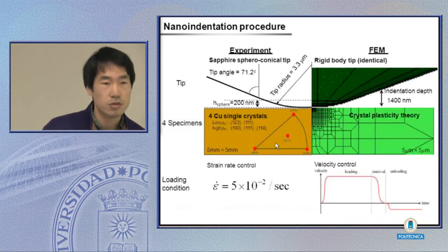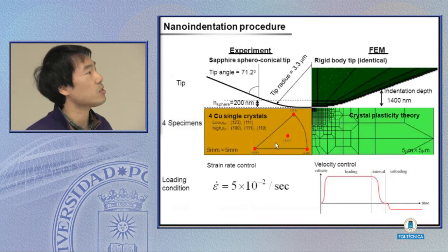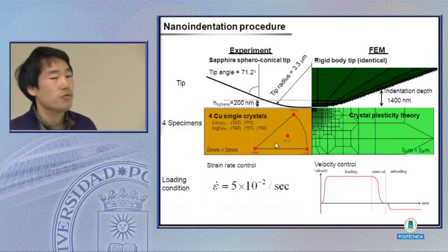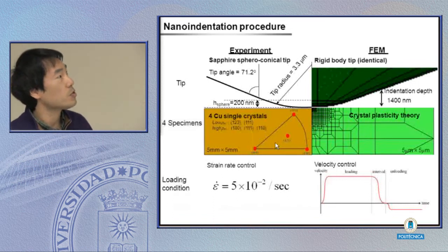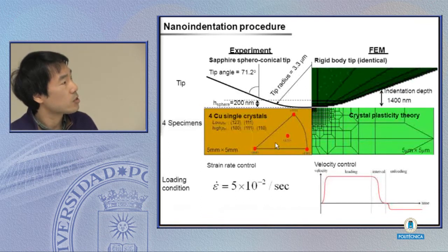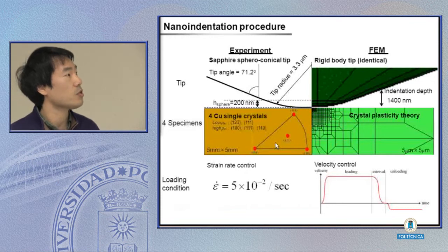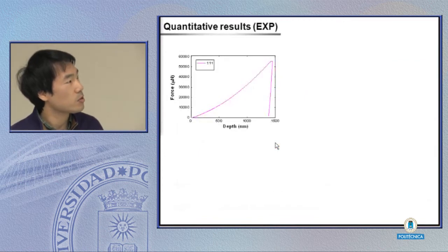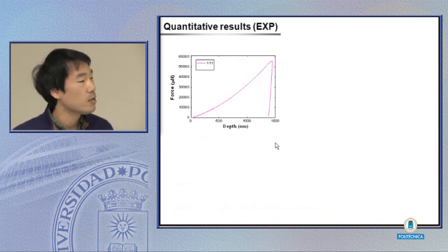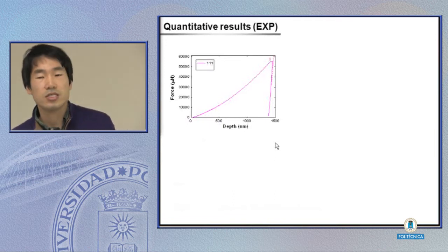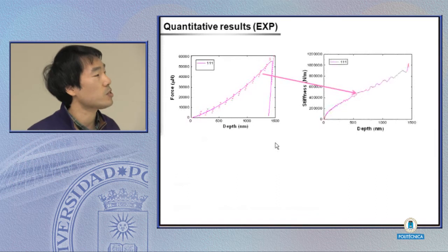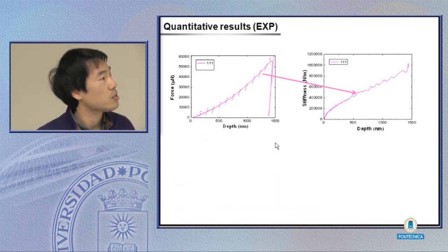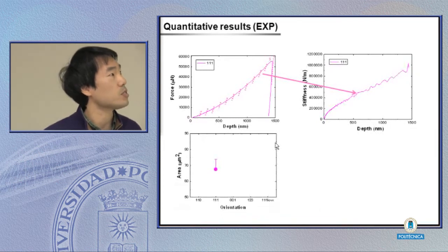And we do a simulation using the crystal plasticity code just like the nano-indentation experiment. So we do a nano-indentation test both experimentally and computationally. In the experimental part, we do a conical tip indentation, and we use 4 types of specimen with 4 different surface orientations and 2 different initial dislocation densities. With the FEM part, we do exactly the same as the experimental test, and we simulate. We compare the result for experimental and FEM result.